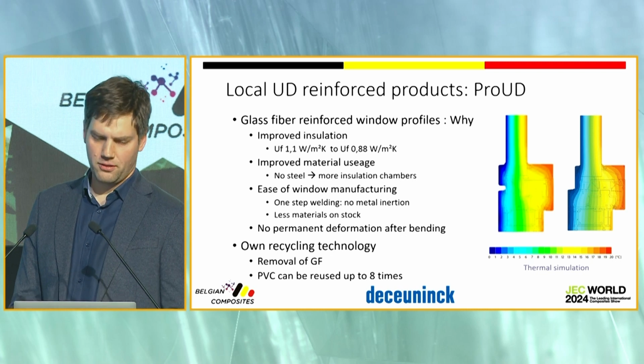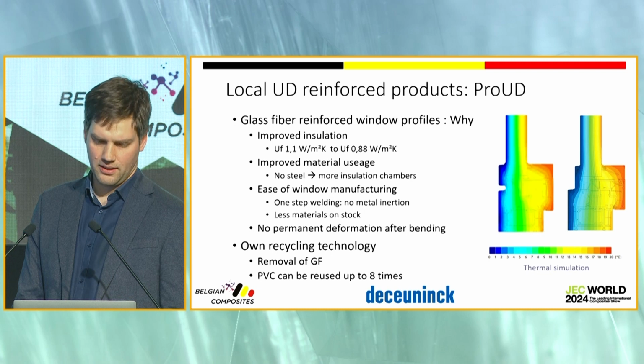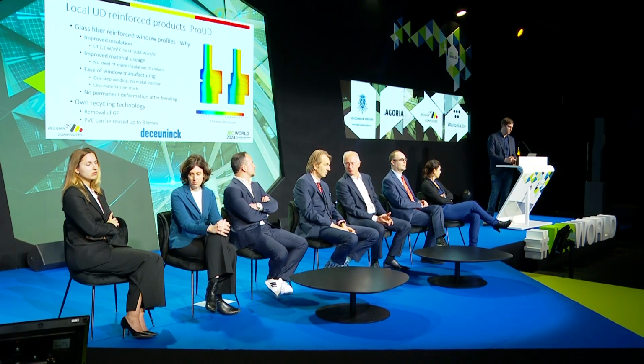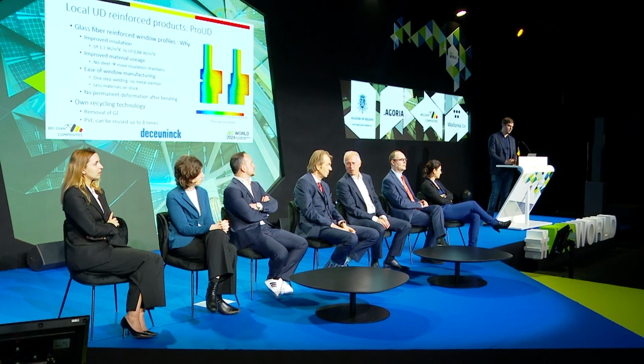And a big benefit of these profiles is that they are easily recyclable. At Deceuninck, we have developed our own recycling line to recycle PVC profiles, but also to cope with the glass fiber which is in these PVC profiles. And we have proven that we can recycle them up to 8 times.